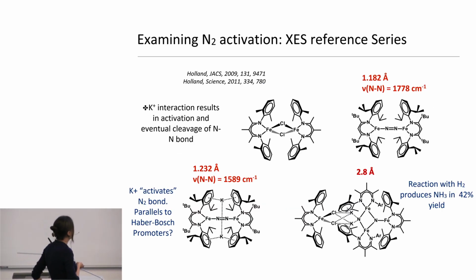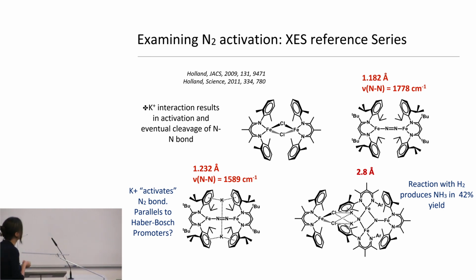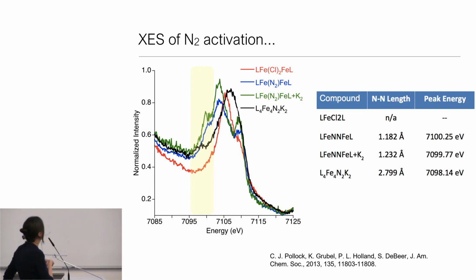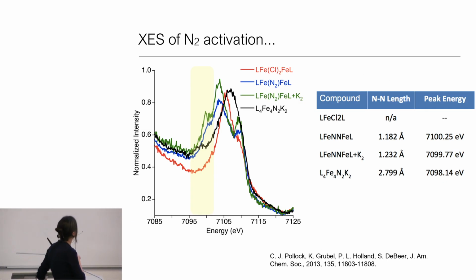And so then we needed molecules to actually test this, and we were fortunate to work with Pat Holland's group, who had a series of complexes that had different degrees of N-N bond activation and even this fully cleaved bis nitride. And what we could see, and these are not the best quality data, these were from that setup we jerry-rigged at CHESS in the early days, but I still like the example because it does show how these features actually shift in energy as a function of N-N bond length.